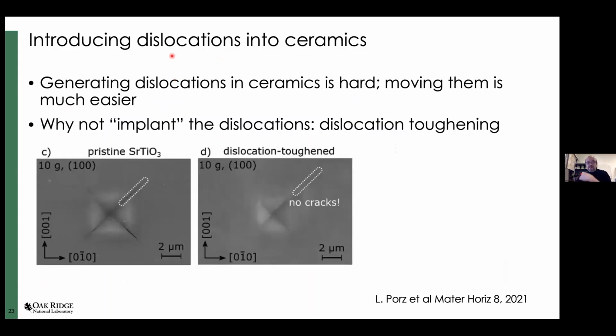So one scenario that is picking up attention in literature, and I think in many cases it's the way to go, is to introduce dislocations into ceramics during the manufacturing. So generating dislocations in ceramics is hard. It's very hard. That's why they fracture so easily. But moving the existing dislocations is much easier. So the question is, why not implant the dislocations? And this procedure is known as dislocation toughening. You can implant dislocations into ceramics just by using different processing methods.